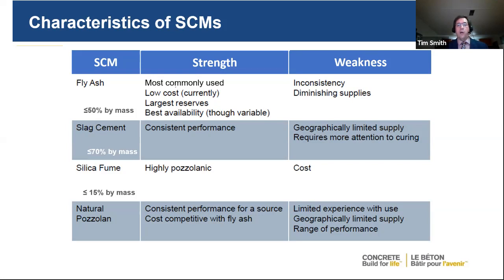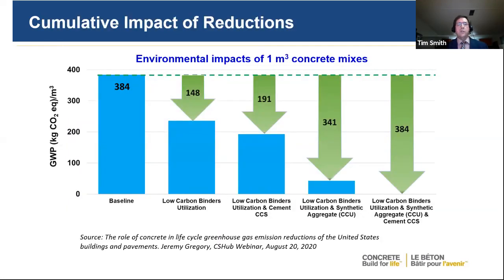Then there's also natural pozzolans, such as metakaolin. There's other ones that we're looking at, and we're also looking at harvested fly ash to ensure that we have a good supply of fly ash available for our concretes in the future. So what does this do then if we start accumulating all these things? If we use the low carbon binders, so if we use the Portland limestone cement with the supplementary cementing materials, we can get a very large reduction in the CO2 attached to that concrete.